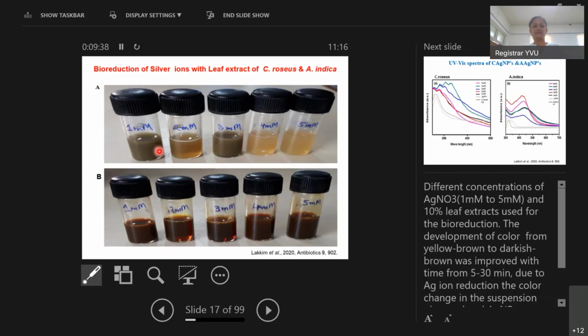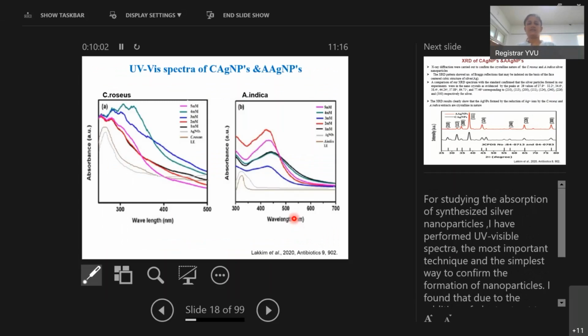The leaf extract undergoes the bioreduction mechanism, and the silver ion color changes from yellow brown to dark brown. This is Catharanthus roseus leaf extract treated with 1 millimolar to 5 millimolar silver nitrate. This is Azadirachta indica leaf extract treated with 1 millimolar to 5 millimolar silver nitrate. This is the UV visible spectrophotometer used for studying the absorption of synthesized silver nanoparticles. I have performed this UV spectrophotometry.